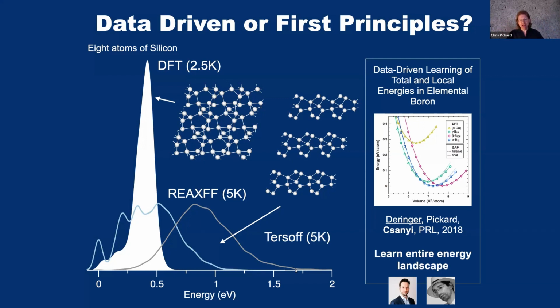And indeed, if you did a random sampling of the Tersoff potential here, you can see that for this gray line, there's very little weight down at zero for the known diamond structure of silicon. So random searching probably wouldn't work for the Tersoff potential. It has too many false minima at high energy that your samples would get trapped in. But in density functional theory, things are smoother, more quantum mechanical, and you slip down the energy landscape. Most of the structures you end up with, although they may be amorphous, are sensible in some sense chemically.